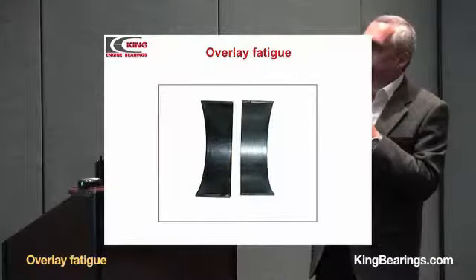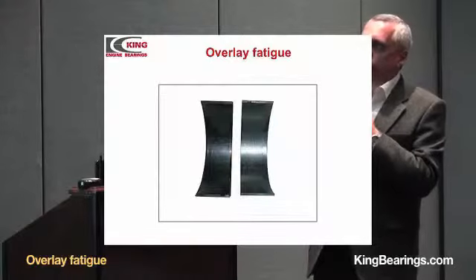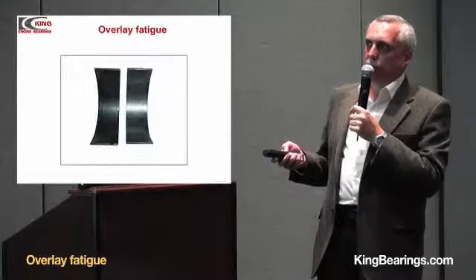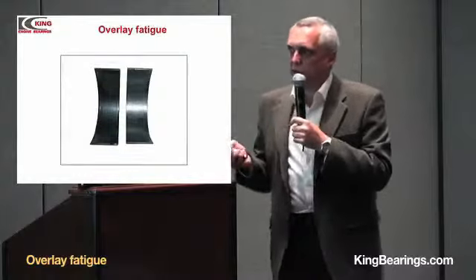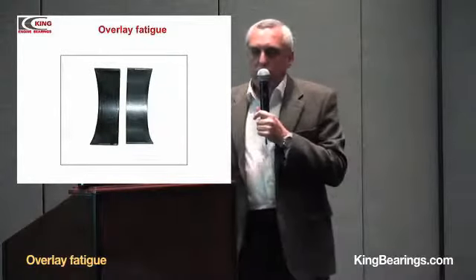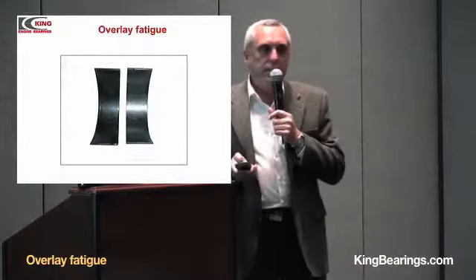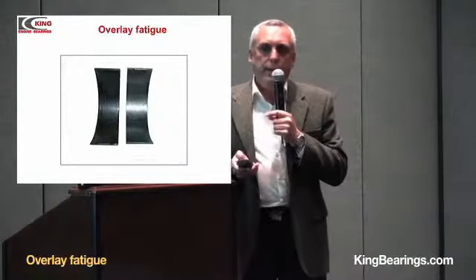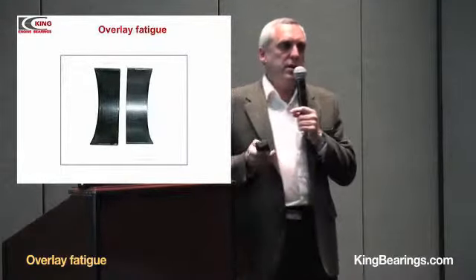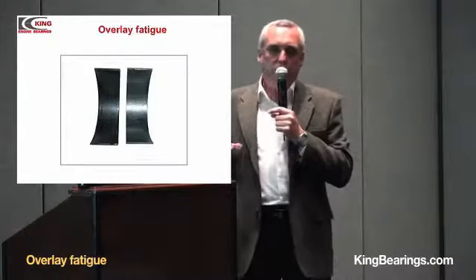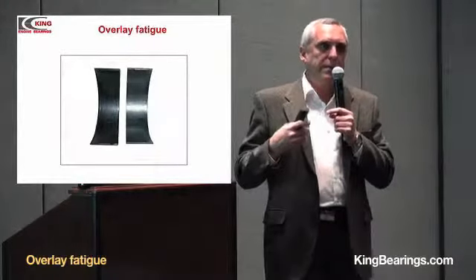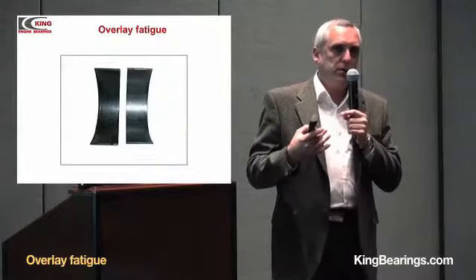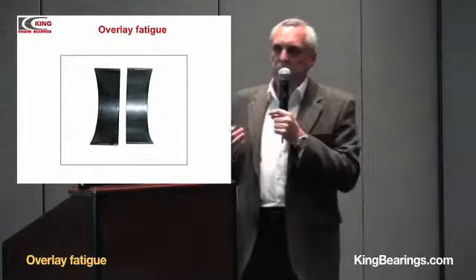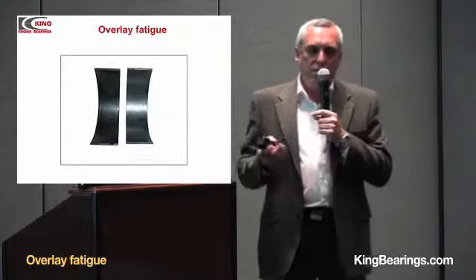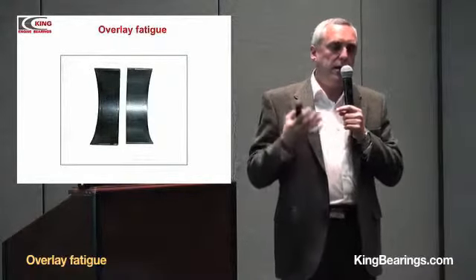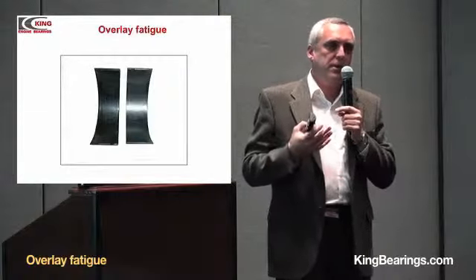You see fatigue on the overlay, the small cracks on the overlay. By the way, fatigue of the overlay is not so bad as it's seen. This process is not catastrophic. If there are some cracks on the overlay, the bearing may continue to work, and may continue to work for pretty good time. It is different from the fatigue of lining, aluminum lining or copper-based intermediate.